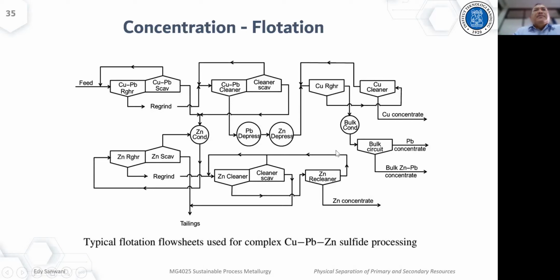Just for example. So usually, once again, in flotation, one stage is not enough. There must be a couple of stages. In designing the flotation process, usually we need extensive experiments for a specific feed in the lab to come up with the design of the flow sheet to run the plant effectively and produce concentrate with the target grade of each element, for example, target of copper, target of lead, target of zinc, according to the requirement.